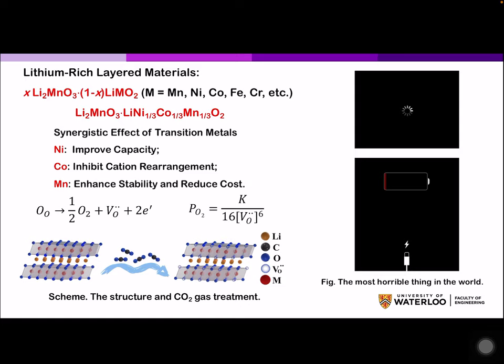However, during the charge and discharge processes, oxygen atoms can be transformed into oxygen gas leaving oxygen vacancies on the surface of the materials. According to the equation, the generated oxygen gas seems very sensitive to the concentration of oxygen vacancies.